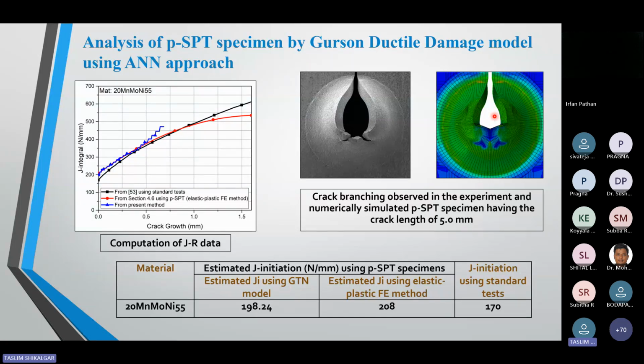During the simulations, I calculated this with the help of the code, and I converted CTOD into the J integral using the conventional correlations. And I plotted this J-R curve. Here you can see my blue curve, which I got from this type of simulation. And I observed that I'm getting the same type of curve that I generated without the damage mechanics model. That is one of the challenges.